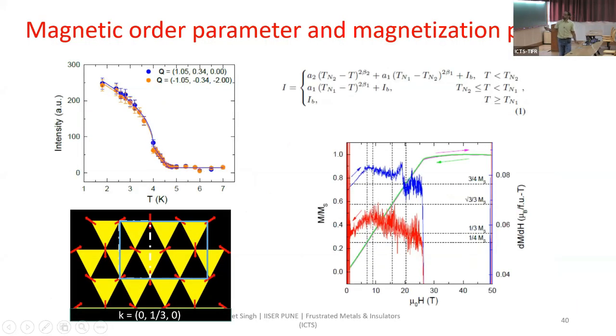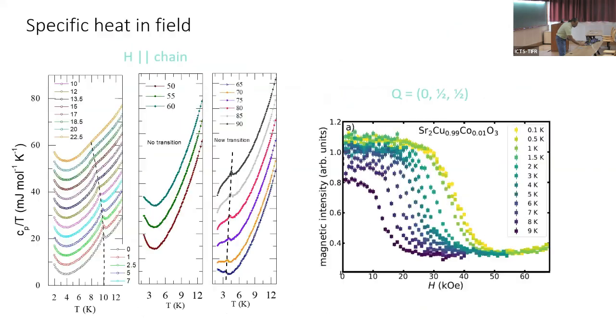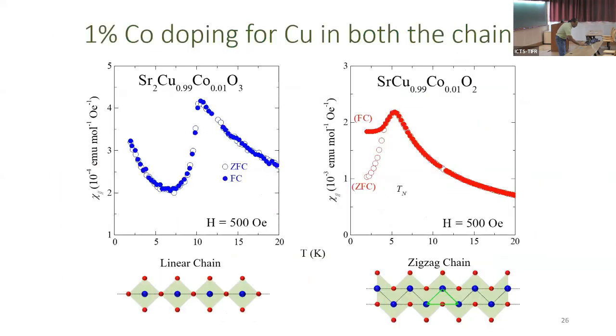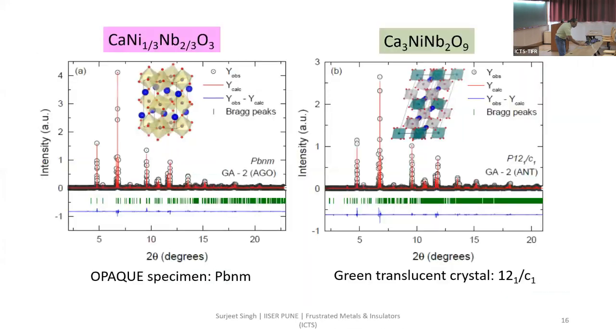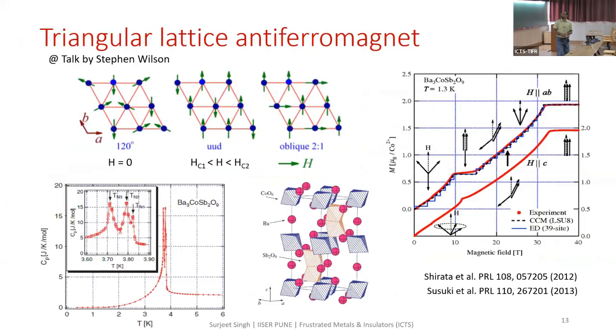So this is the neutron data, which is done with Marcos at Garching. And this is the magnetization curve in the ramp up and ramp down field. And here you see the 1/3 magnetization plateau. But in addition to that, you see other features, which is not very unusual because in these triangular lattice antiferromagnets, you can have a cascade of transitions, which I showed here also. As you can see here, you get a series of transitions until you go to the fully polarized field.